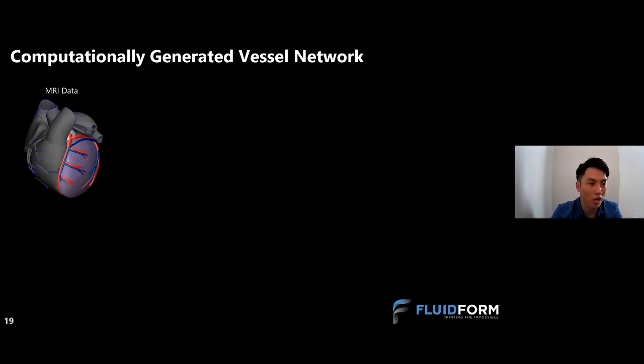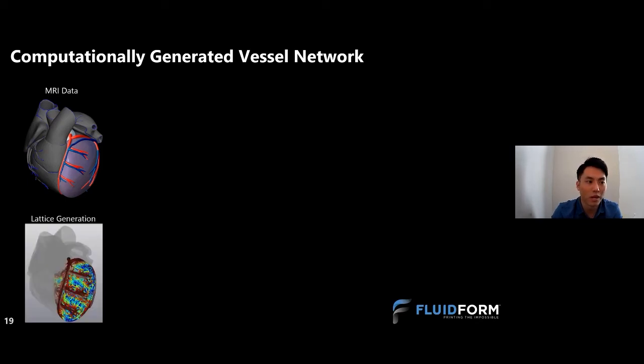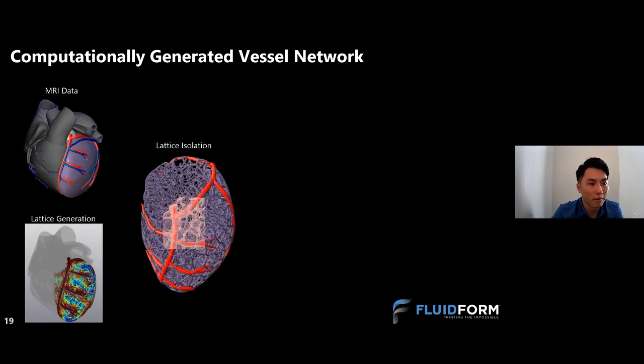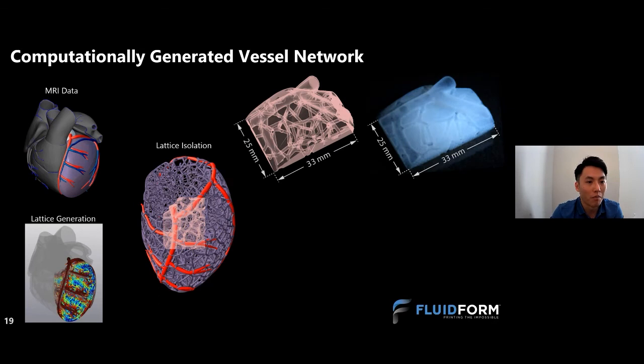So again, we took MRI data. With MRI data, there's this caveat that it can't pick up a lot of the high resolution details, such as the capillaries that you might find within your heart structure. So we took the MRI data and computationally generated some of the smaller vessel networks that aren't resolvable in MRI. And so we then segmented it out and took a piece of this lattice, this vasculature network, and we actually just printed it. So you can see here, our print resembles very much the original design file.